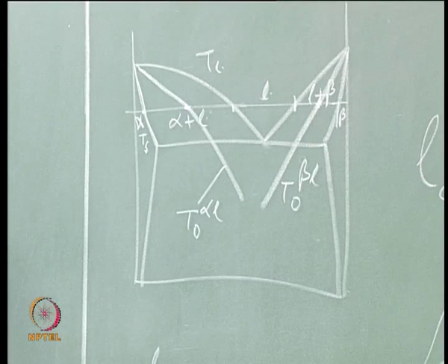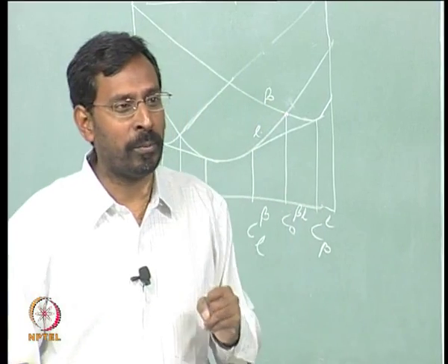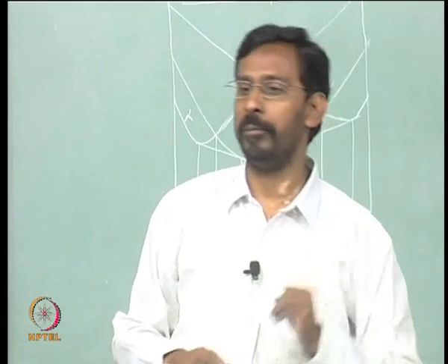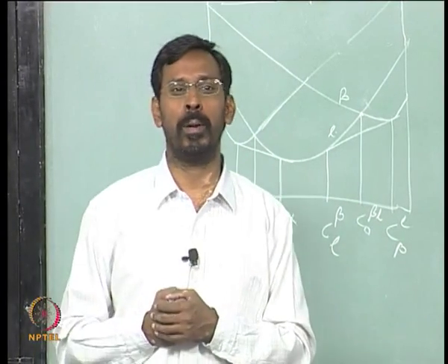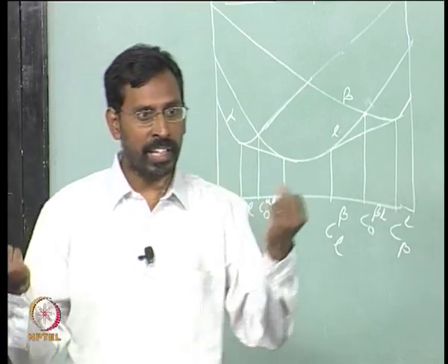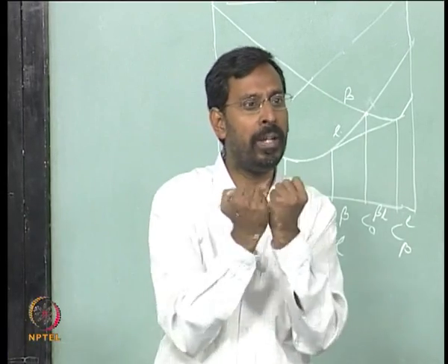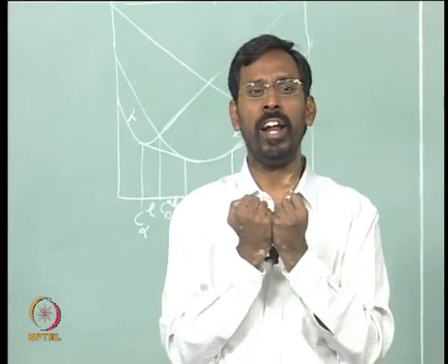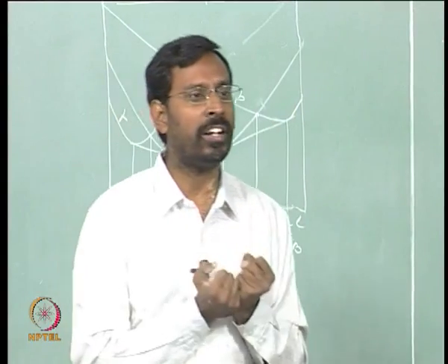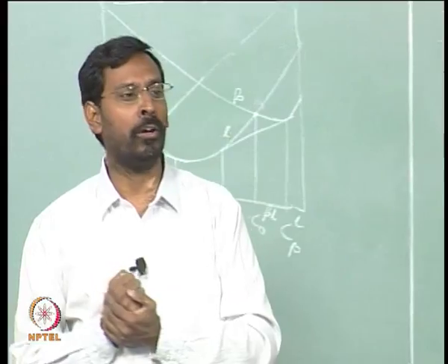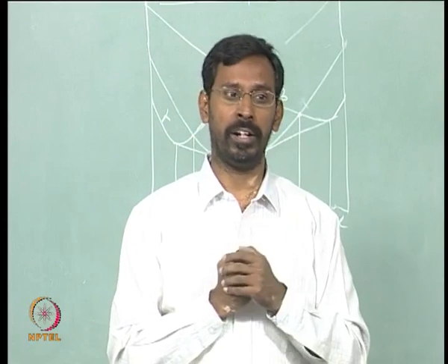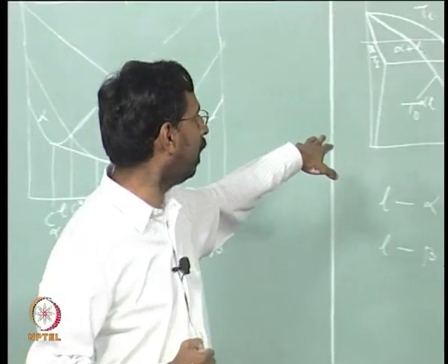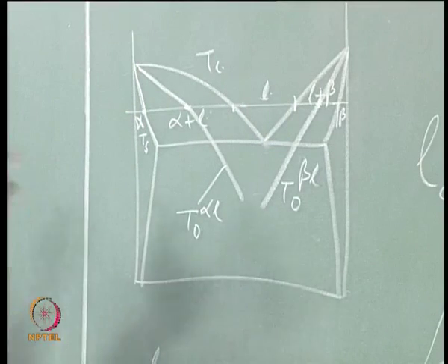What is the experimental data that you need? Cp and one more. For a solid solution you need one more data, omega. Omega is the delta H mixing. So, delta H mixing also comes from experiments. That means when I take A and B, whether A and B have an attractive interaction or repulsive interaction, how much is that interaction can again be obtained from calorimetry.